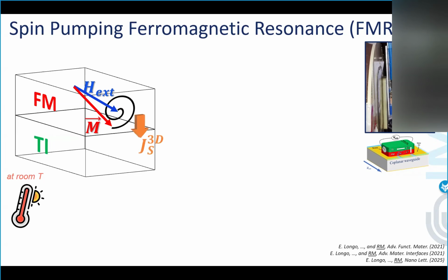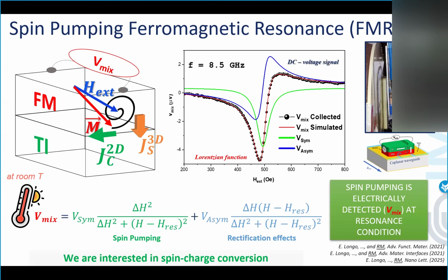In ferromagnetic resonance, you put a ferromagnet in contact with a topological insulator, because in these devices you need to convert pure spin current into pure charge current and vice versa. This is a very intimate process that makes your device work. And one of the ways of measuring this kind of conversion is ferromagnetic resonance. So very briefly, you want to see a symmetric contribution to your signal, which then reverses if you reverse the sign of your applied magnetic field. This is a clear proof of a spin-dependent process in the conversion.